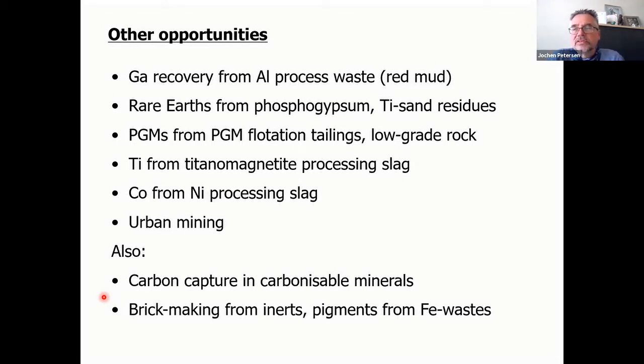Titanium sand residues, the beach sands that you process are enriched in order to extract ilmenite and zircon phases, but the residue contains a significant portion of rare earths.